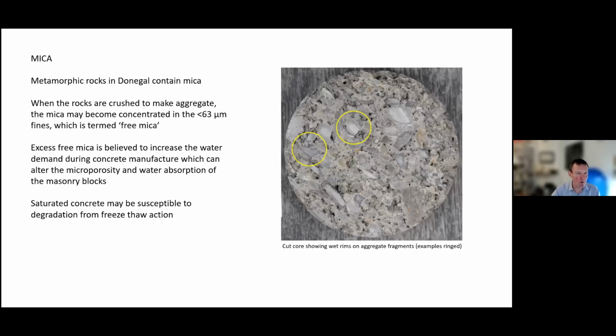The Donegal metamorphic rocks are mica-bearing, and when these rocks are crushed to make aggregate, they liberate quite a lot of fines, which are grains that are less than 63 microns, termed free mica. And it's believed that this excess free mica will increase the water demand during concrete manufacture. And this can alter the microporosity of it and the water absorption of the finished concrete masonry blocks. And following on from that, IS 465 says that saturated concrete may be susceptible to degradation from freeze thaw action.